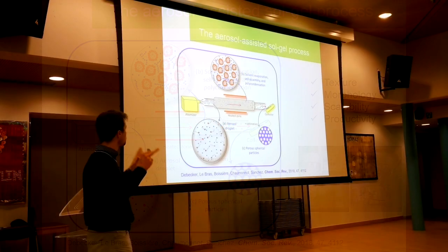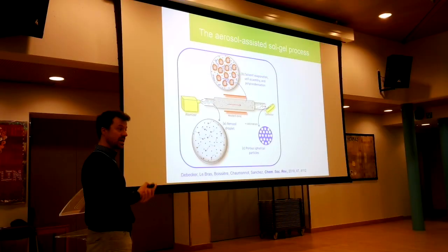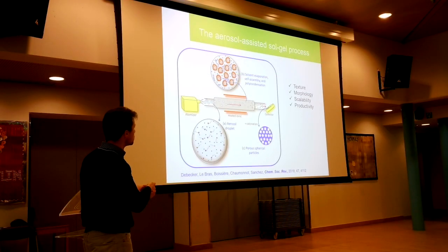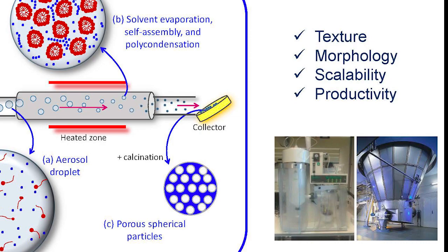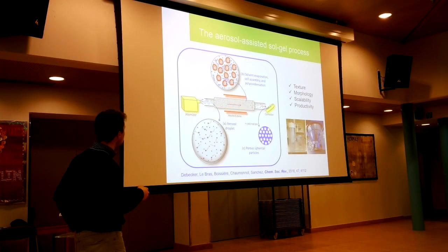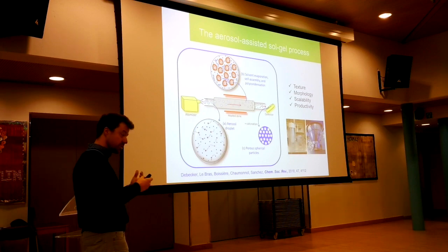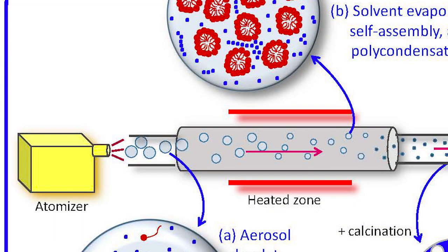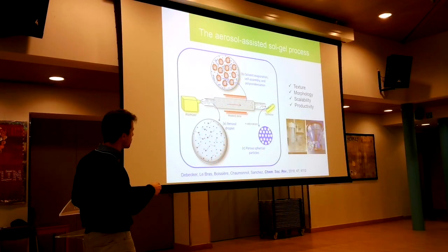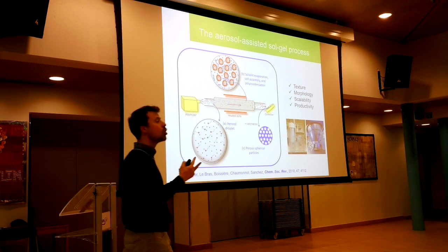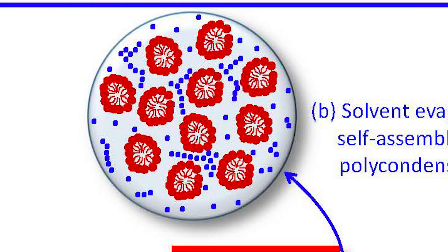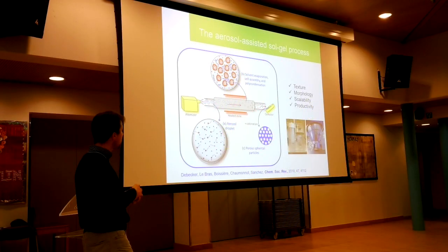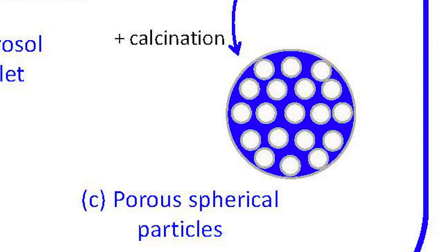It's a bit special. It's called the aerosol-assisted sol-gel process to make heterogeneous catalysts. What we want to have in the end is a catalyst with an excellent control on the texture, so the porosity, the morphology, and something that could be easy to scale up and to bring to industry. So how it works: we start with molecular precursors, so not solids, and we spray them, we atomize them as small droplets, which are dried very quickly. And in here, we also put some surfactants. Those surfactants, or soap molecules if you want, amphiphilic molecules, will make micelles, right? And around those micelles, we will build the inorganic solid, to get, in the end, after calcination, when we remove the surfactant, pores that are calibrated with the right size for catalysts.